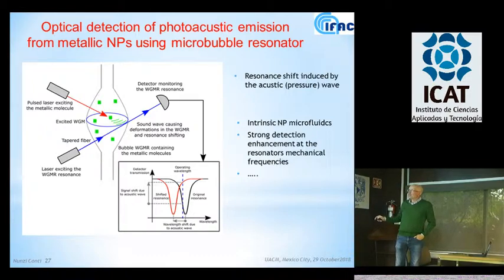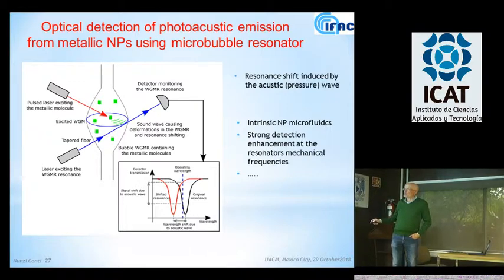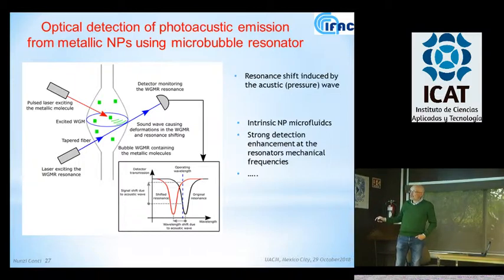Basically, it's to use this bubble resonator for microfluidics, and here we have metallic nanoparticles that are excited, so there are photoacoustic waves that basically produce oscillation in our bubble, which can be read simply by using a coupled fiber, because when the wave hits the resonator, it changes the resonance position by changing the index or the size, and so you end up with a shift, and by using your laser at a certain wavelength, you can translate this shift into a change in the power.